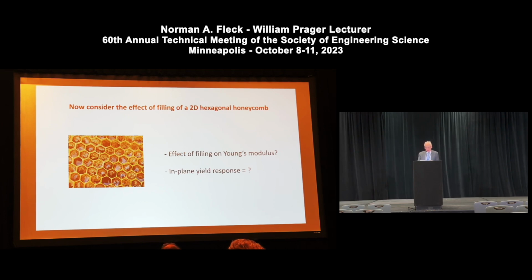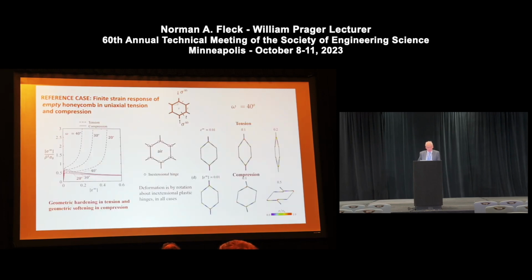So we took a two-dimensional honeycomb. Just for reference, I'm plotting here the stress-strain curve of the empty hexagonal honeycomb. There's a major parameter here, omega, the inclination of that cell wall. For a regular hexagonal honeycomb, omega is 30 degrees. But we can vary that and end up with an anisotropic honeycomb. So if it's 20 degrees, that value is less. And we can also take 40 degrees, in which case it's greater than the regular hexagonal honeycomb of 30 degrees.